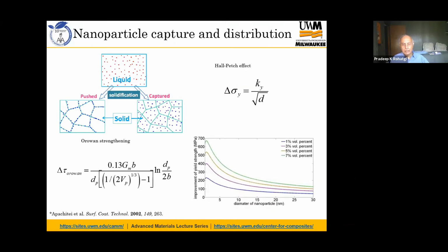And why nanocomposites? Because they can give you better properties than microcomposite, because the distance between the particles is nano size rather than micro size. Here is an example. I was talking about whether the particles will be pushed by the solid liquid interface or whether they'll be captured. And if they are pushed, all the reinforcements will be at the grain boundaries. It will not give you that much improvement in properties if they were engulfed and these nanoparticles were within the grains. So that is an effect of whether the particles are pushed or whether they are captured. Ideally, you would like the particles to be captured and within the matrix and within the grains.